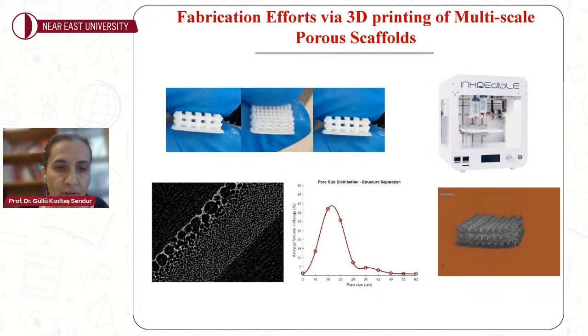And what you see down here are different geometries with multi-scale porosities, both on the macro and micro level. Again, you see scaffolds that we fabricated using a bioplotter, where we made our solutions by dissolving PCL and nHA. We don't dissolve nHA. We mix PCL and nHA in a solvent and then plot it in ethanol to undergo phase separation that would induce pores at different sizes, which we analyze using our micro-CT tomograph in our lab.